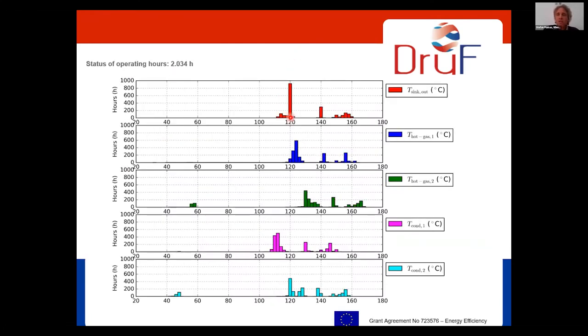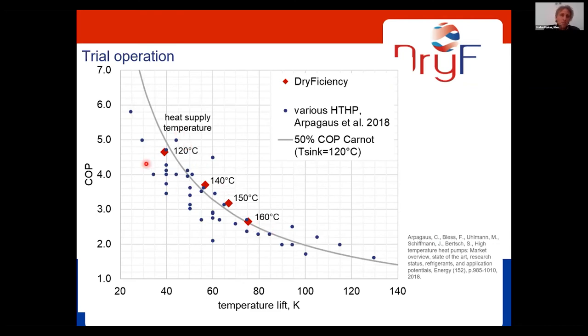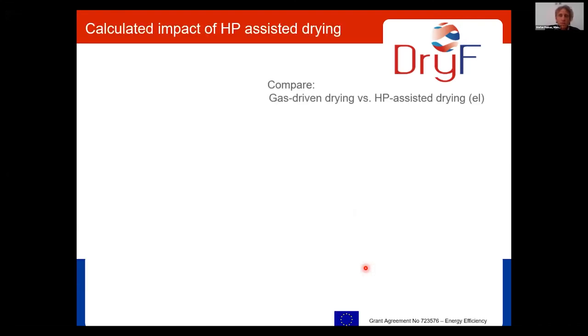Here you see the temperatures we operated on. The 160 degrees was the target. We proved that it works well, but the energy consumption is quite high. And we pay much more for the electricity compared to AGRANA. So most of the time we operated at 120 degrees sink temperature. And when we compare the COP to market available heat pumps, we see that the DryFiciency heat pump performs quite well and additionally provides higher temperatures than market available ones.